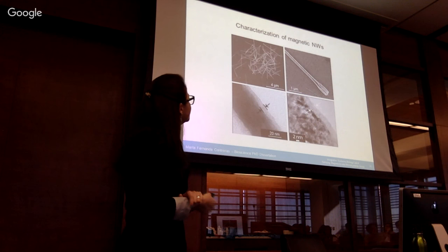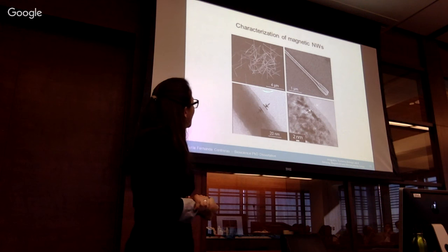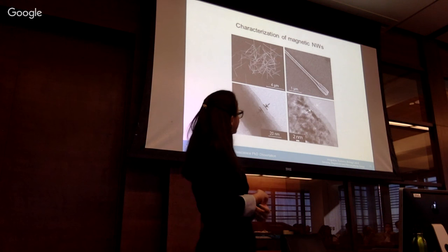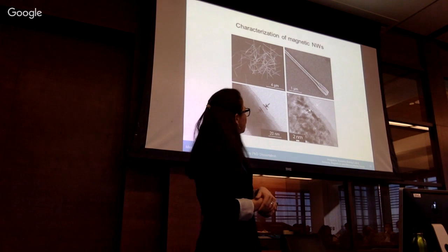Okay, here are some electron microscope images of the wires. The top two are SEM. The bottom two are transmission electron microscope images, or TEM. Here you can see released nanowires on top of a silicon wafer. These are nickel nanowires. And the second image is a detail of the dendrites I mentioned to you before, the step prior to the deposition. So you can see how they look.